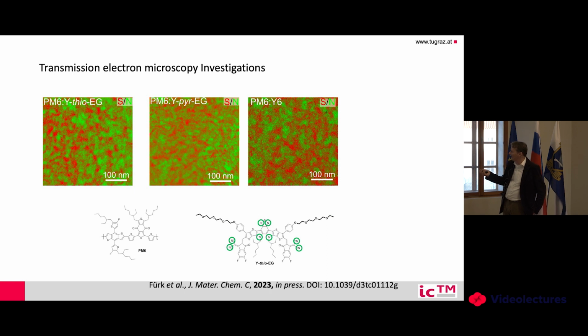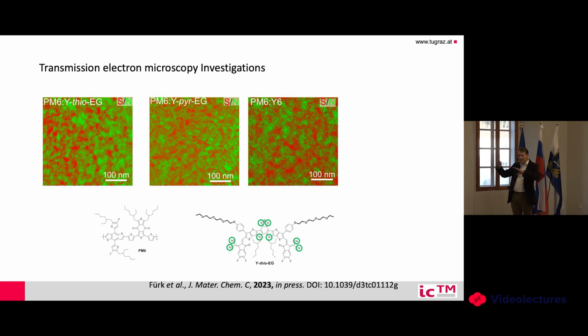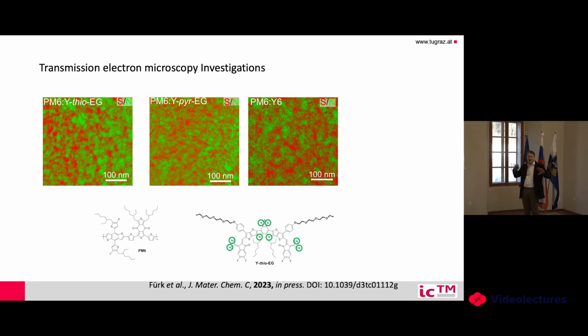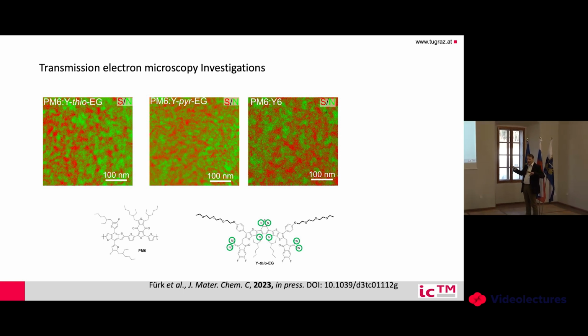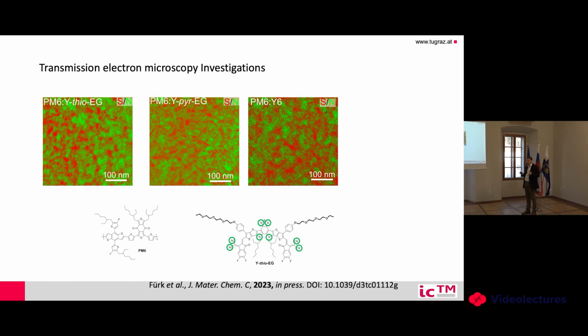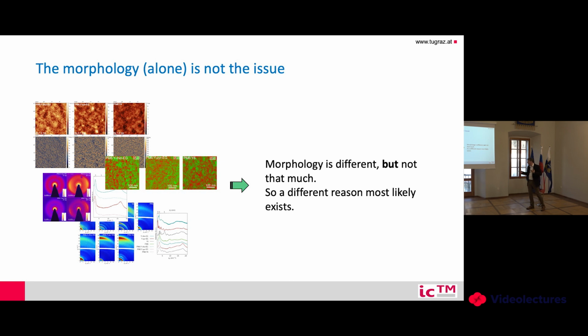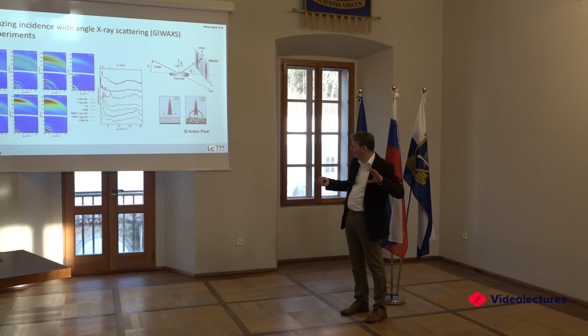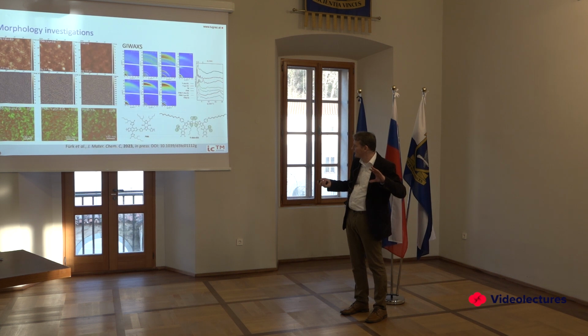You see the green and the red are the two different phases. You see similar structures. And from experience, this cannot explain these very large differences. So we were really a little bit lost, so we didn't know what really happens, because the electronic structure of the material is totally the same. This I forgot to say. So this, where is the structure? I just go back.